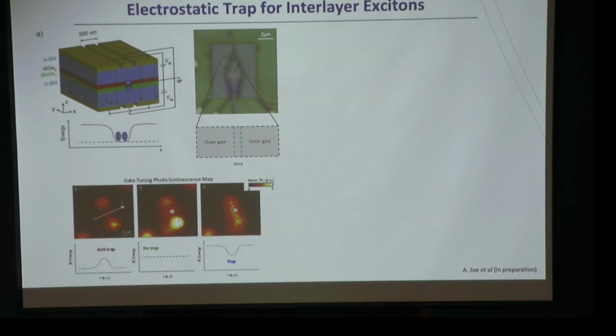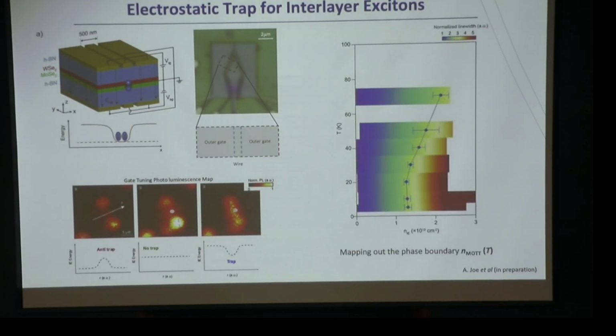And by controlling the exciton density and studying the exciton density as a function of temperature, we start to see when the excitons dissociate and give us light, and we start to draw part of this exciton phase diagram as a function of density and temperature. Okay, this is rather indirect at this point, and there is quite a recent measurement done in Fai Mak's group by transport, just mapping out these phases. But that gives us the way that just by having this type of 2D materials and structures, we can start to study these composite bosons and their condensation.